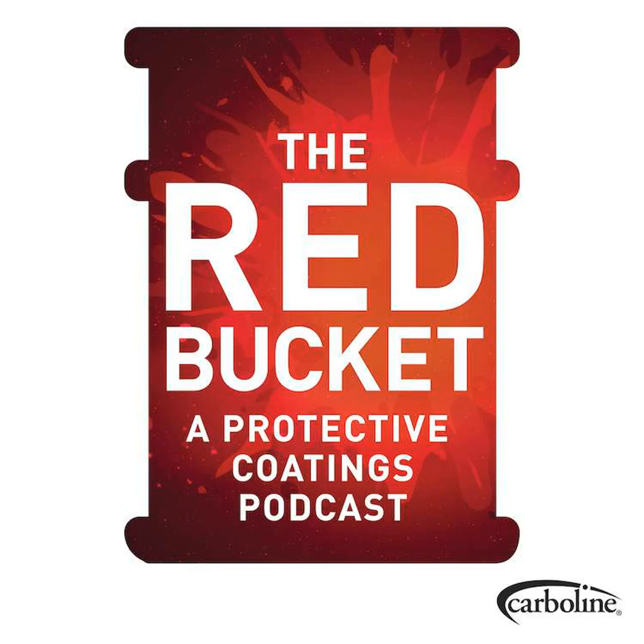So you don't need literal 100% coverage by zinc of the substrate, and the zinc can be intermittent, it would still perform its function? Yes. And in fact, what we do in our testing of zinc-rich primers is we actually take a standardized scribe tool, because we're very standardized in the paint industry. And we take that tool and we cut into the coating system to expose bare metal. And that is to show in our testing that the galvanic cell is able to be formed and that corrosion protection can occur.